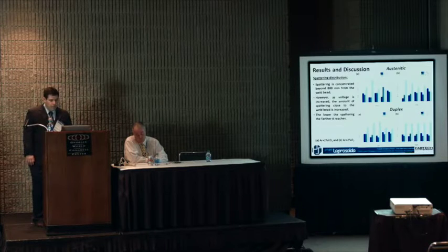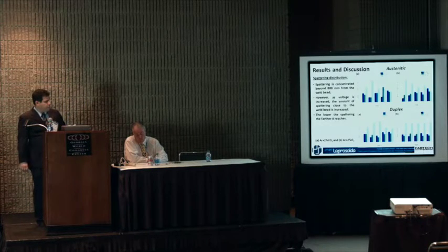If you look here, okay, it's not properly statistical, you cannot say that. But we see a trend for higher deposition efficiency for the smaller wire feed speed, and for argon plus 2% CO2, which is something that we expect, that 2% CO2 would be better than 2% O2 for short circuit metal transfer. We make an analysis of how far the spattering goes.